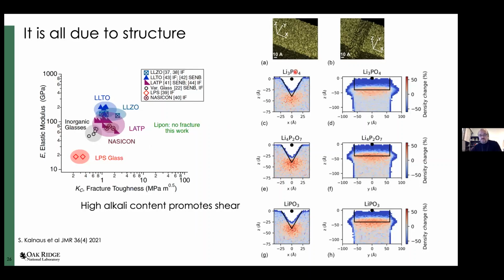So using MD simulations, you can look at different compositions and see how the deformation partitions into the densification and shear. This is, of course, a simplified case. This is not truly nanoindentation. You have a slab of material and you have a wedge going inside, but judging by the material pileup at the edges, you can tell about shear deformation, and judging by the densification, the average distance between the tetrahedra under the indenter, you can see how much densification is occurring. And all the simulations are unfortunately done without nitrogen, simply because the force field for compositions with nitrogen is not known. But we don't believe nitrogen would change this behavior too much.